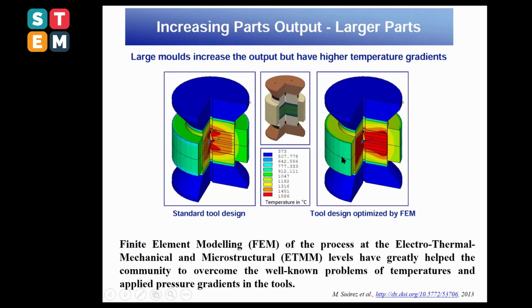And then they were able to optimize the tools, where you can clearly observe here, you should be able, by finite element modeling, to optimize this thermal gradient. And this was why they succeeded to produce a batch of samples, many samples at the same time.